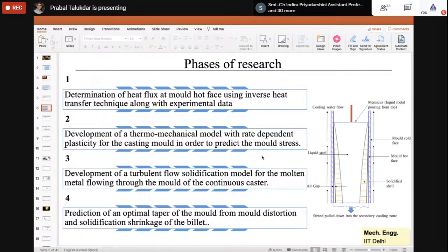The first one, I think this diagram is a little more elaborate, so I have to explain this diagram again. This is the jet through which the liquid metal comes. Normally from the tundish, through a jet, the liquid metal is poured into the mold. This is the liquid steel. In between, the yellow dash is the solidified shell, which I am mentioning as the strand. This is the solidified shell or solidified strand.